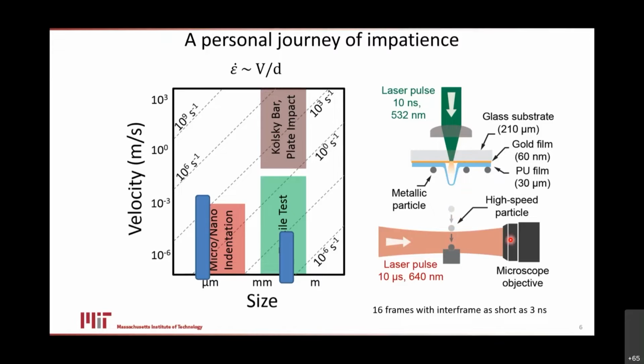And when we started talking, they were in the throes of setting up a new camera, which had an incredible 3 nanosecond interframe time spacing so that you can get incredible fidelity measurements of particles as they fly and as they crash into a substrate. So as a mechanical testing kind of person, I looked at this and I said, wow, this is it, because look where this falls on the map over here. We're talking now about doing essentially micro or nanoscale indentations, but we're able to launch these particles at velocities that are in the hundreds of meters per second up to kilometers per second. And in fact, nothing I talk about today will be at a strain rate below 10 to the sixth per second. So very high strain rate testing. In fact, higher than you can normally get quantitative data with a Kolsky bar or an impact system.